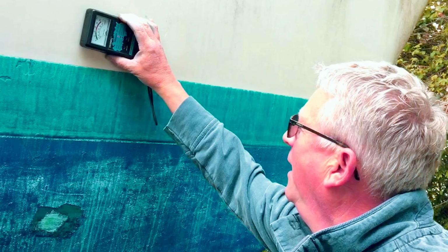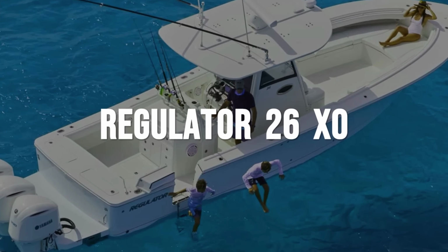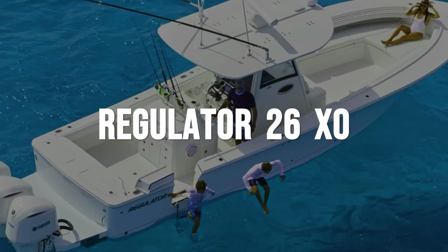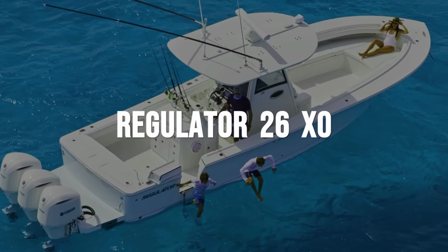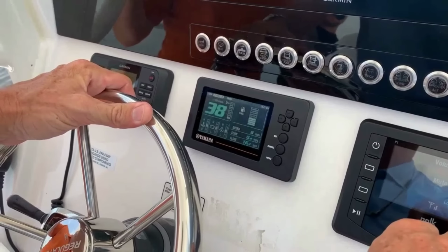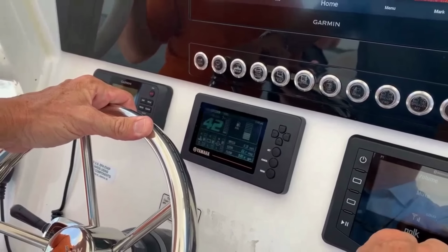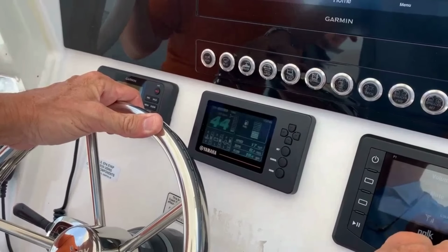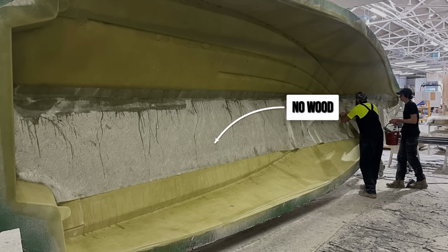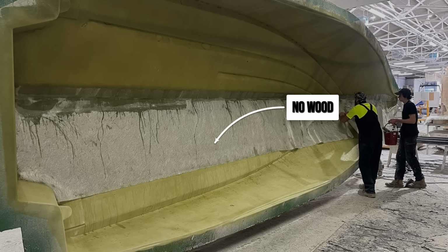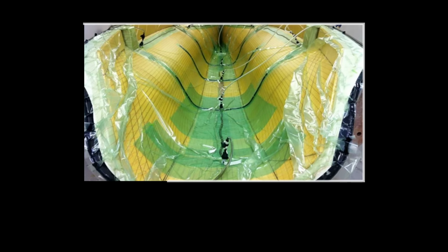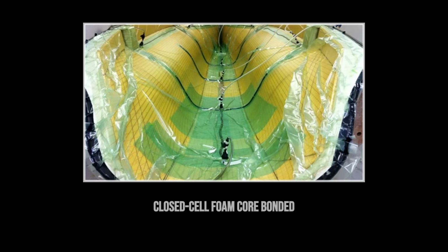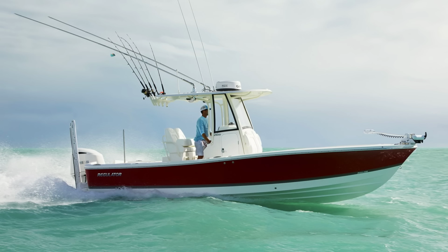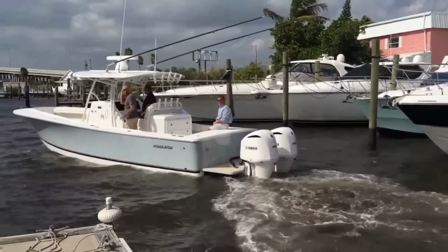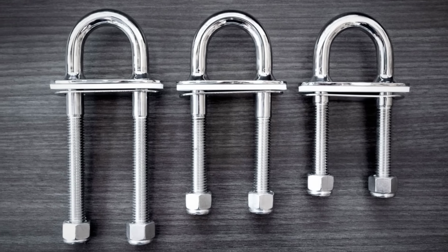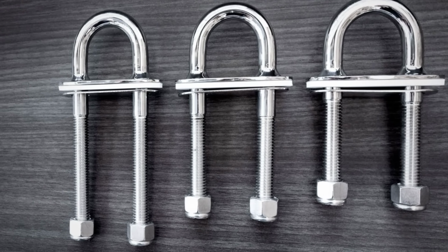The same construction standard that defines the 31 applies to every regulator in the lineup, including the 26XO. It brings offshore class hull engineering into a size category accessible to a broader range of buyers. 1 solid piece fiberglass stringer, no wood, bonded in the hull while still in the mold, foam injected, and cured as a structure with the hull and liner. The Lou Codega 24-degree deep V hull geometry is confirmed across all models. 316 stainless steel through bolted hardware is used at every penetration.